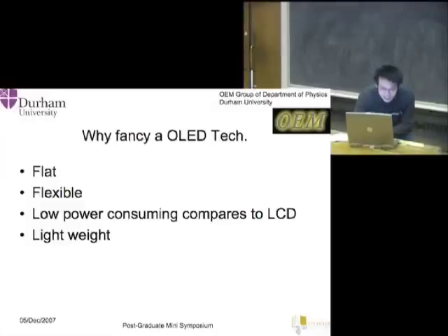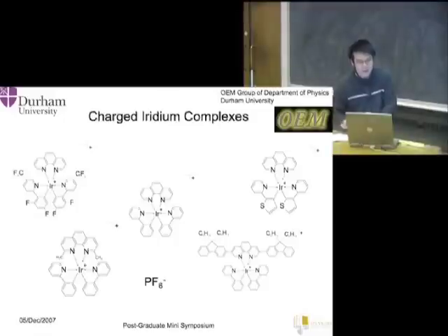And this kind of thing has the name organic in it because it really has some structure that looks like this. Most of the small molecules we use in this field have structures like this or this, with a lot of pi bonds, and these pi bonds standing on each carbon atom would overlap, so the electrons can go through this area. And then in the film, electrons can even hop from one molecule to another molecule, so that makes the whole film conductive.